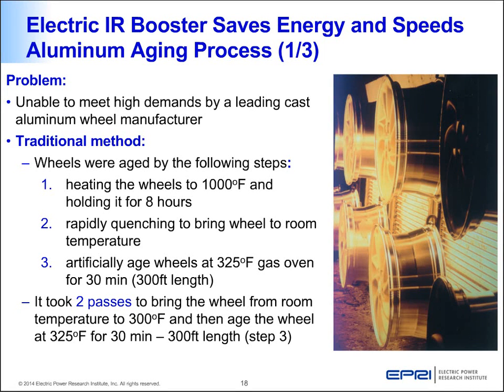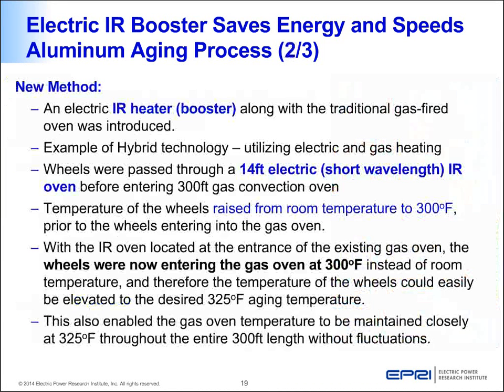The bottleneck was found to be step number 3, where the wheel has to go through two passes through the 300 feet length gas oven in order to reach 325 degrees. So this was discussed with the electric infrared vendors, and a new method was formed. In the new method, they still retained the existing gas oven, but a hybrid solution was proposed. In the hybrid solution, an electric infrared heater, a shortwave infrared oven, was introduced just before the gas oven.